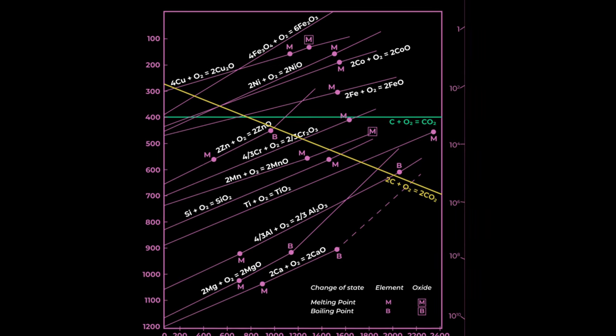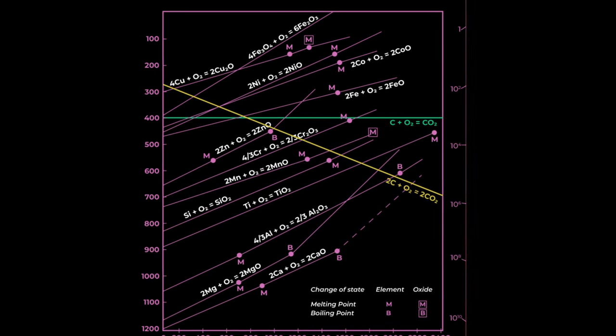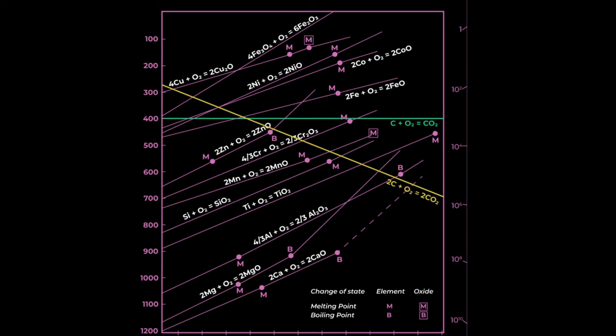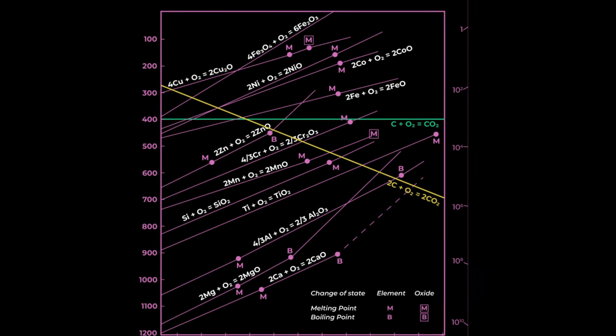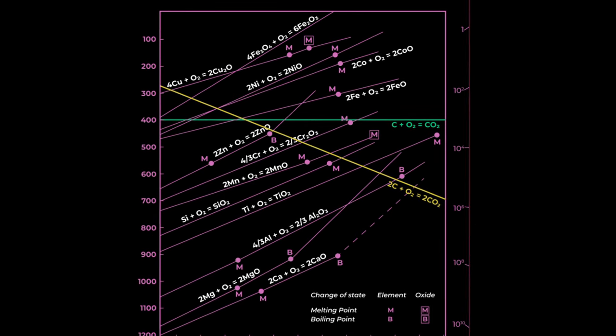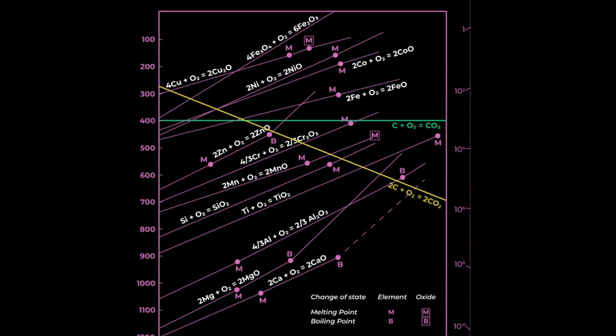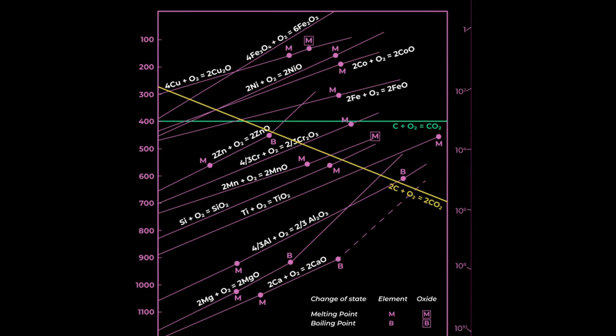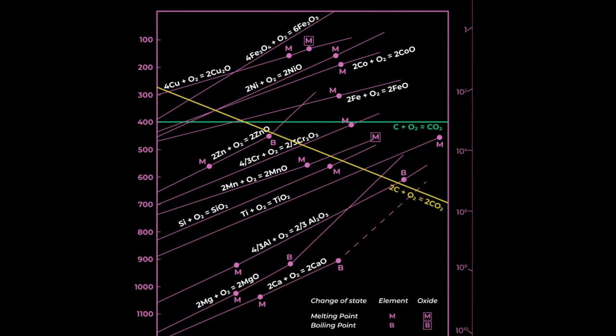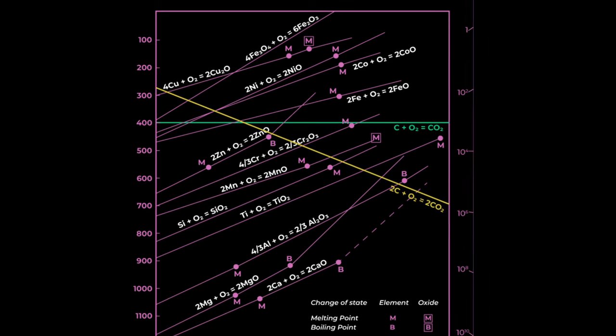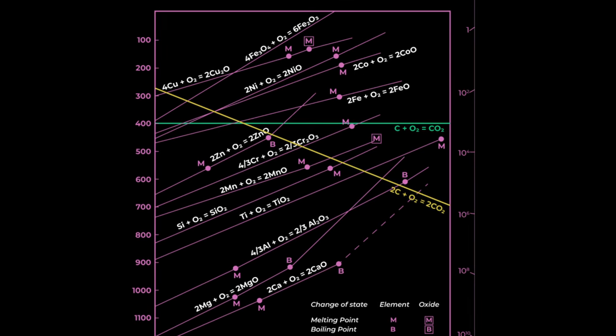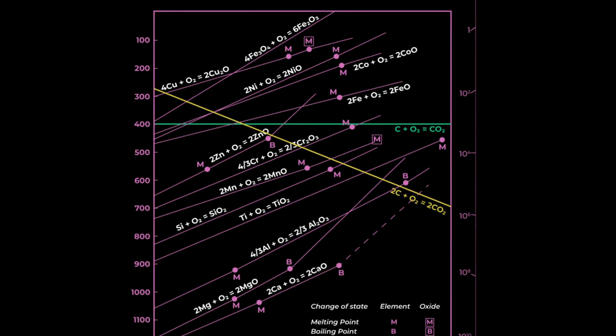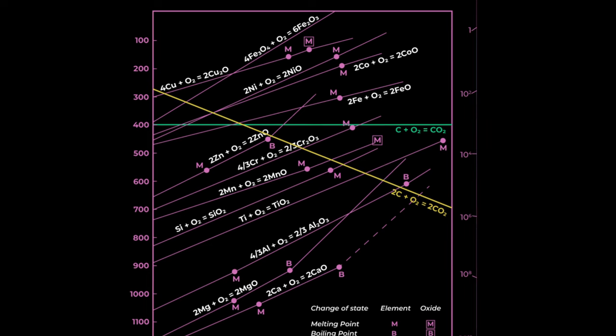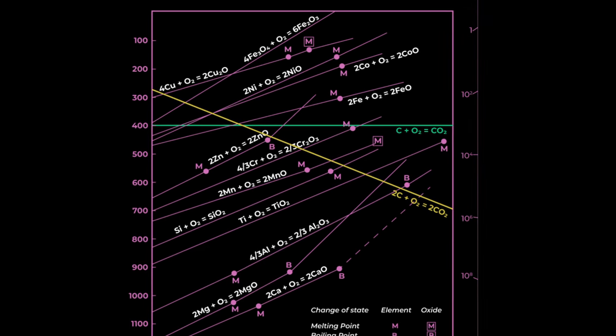At temperatures over 1600 degrees, which is quite attainable using concentrated sunlight on the moon, everything has melted and so everything will be reduced and reduce the next thing in line. Since there's only a limited amount of oxygen in the regolith, it will shift up the reactivity series, leaving those at the top of the chart without. Or I guess you could say it will shift down the Ellingham diagram.